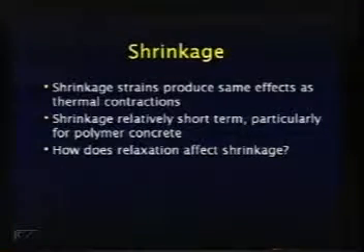Now, shrinkage is relatively short term, particularly for polymer concrete. We know that generally shrinkage occurs over a matter of a few hours or a few days. For Portland cement concrete, it may occur over months or maybe even many months. But the question was, how does relaxation affect shrinkage?